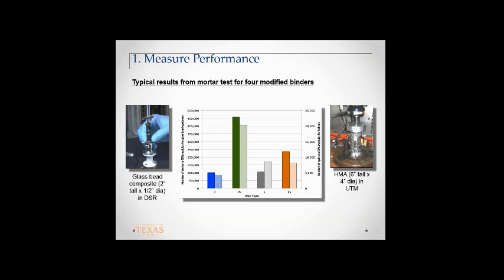The bars on the right correspond to full mixture tests using a push-pull type system with viscoelastic continuum damage, using an asphalt material performance test, an AMPT type of device. So you'd have to fabricate full asphalt mixtures using Superpave gyratory compactors. You'd have to glue the end plates and run all of these tests on full asphalt mixtures.